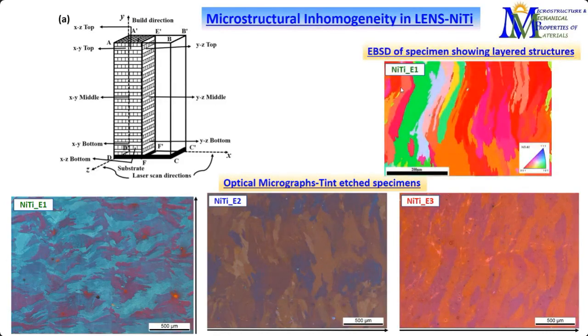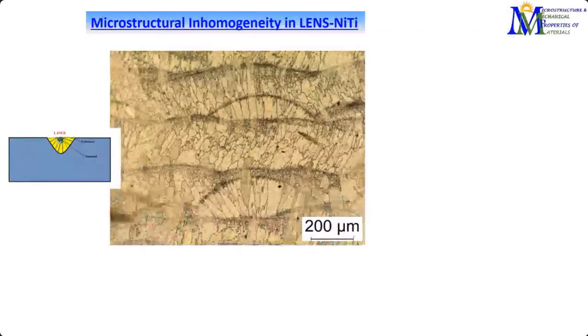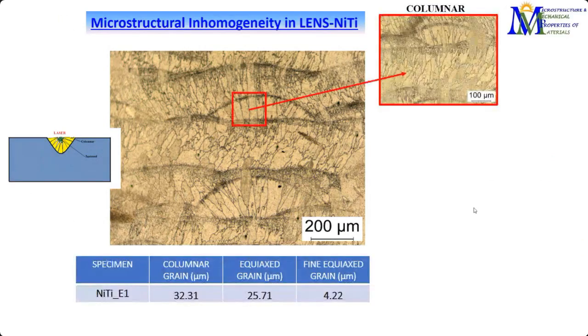This is the EBSD image, which shows this layer structure very clearly. Going into more detail, we've seen this kind of layered structure with hatches present, very distinctly visible. Based on the laser tip, we generate these kinds of hatch structures.